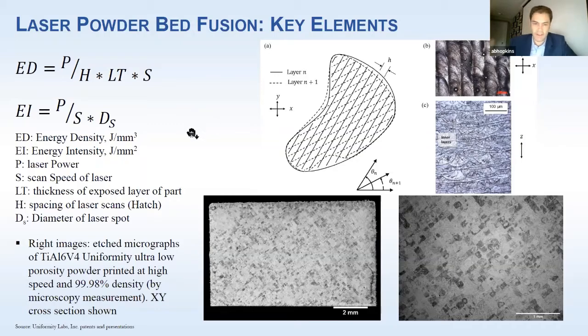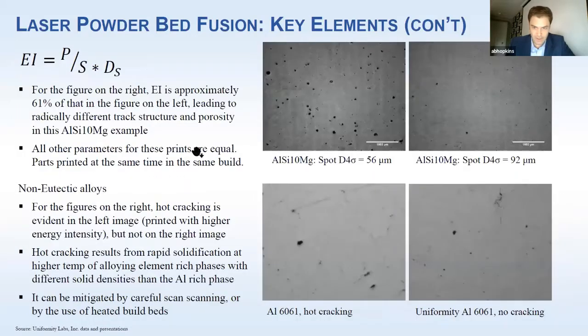So if you think about drilling that hole I was talking about earlier, as it heats the materials adjacent to it, you actually get a dependence. It's linear, it's not on the square. So we introduce energy intensity in joules per millimeter squared. In this case, again, the DS is the spot size. This matters because if your energy intensity is too high, you'll overheat aluminum. I think I've got a chart here.